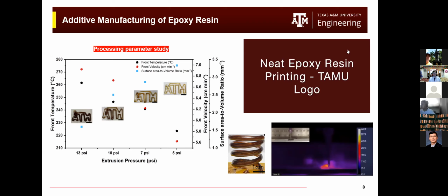May I have a question, Ruochen? Yes, please. In this 3D printing, is it easy to clean your nozzle, as long as the viscosity is very low, right? Yes. I think that's a good question, because in my experiment I came across the nozzle being jammed by the frontal curing propagating through the nozzle, but it seldom happened. If the reaction propagates into the nozzle, the heat release will be significantly higher than it is on the substrate, so the front seldom penetrates into the nozzle. However, if it's jammed, it's a problem, because the resin is cured. So yes, that sometimes happens.